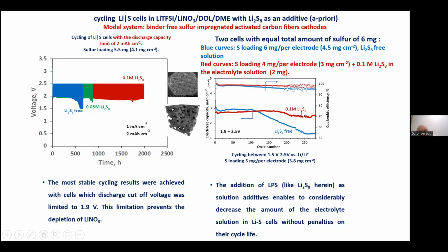Again, we have complex surface chemistry which forms networking on the surface and stabilization by flexible surface films that accommodate the morphological change and also avoid continuous reduction of lithium-sulfur species, which are formed by reduction of sulfur. We can use encapsulation of sulfur in carbonaceous material. This is carbon cloth, which is highly activated. So we can reach something like 60% sulfur, coming up with systems with relatively high energy density under optimization. And now we compare.